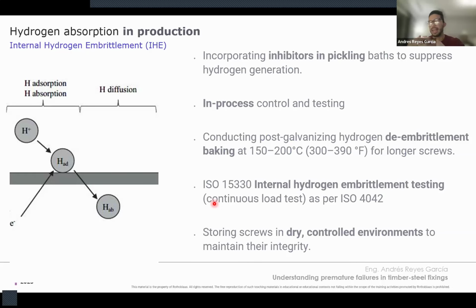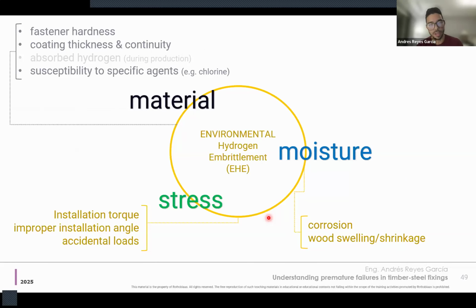But I really don't want to get too much into detail with this part, because this is the manufacturer's responsibility. What we do, which is mostly state of the art in the industry, is incorporate inhibitors in the pickling baths, and a lot of in-process control and testing. For some screws, we have de-embrittlement baking. Also, internal hydrogen embrittlement testing is fundamental as per ISO 15330, and then storing the screws in dry and controlled environments to maintain their integrity. And that's it for internal.